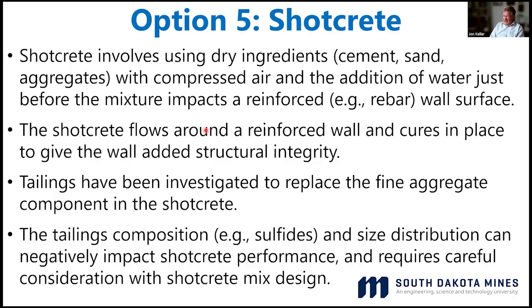Option 5 is shotcrete. Shotcrete involves using dry ingredients, cement, sand, aggregates with compressed air and addition of water just before the mixture impacts a reinforced wall surface, typically with rebar. And so the shotcrete flows around the reinforced wall and cures in place to give the wall structural integrity. Tailings have been investigated to replace the fine aggregate component in the shotcrete. But once again, you have to worry about sulfides and particle size distribution. I found just a few references where shotcrete was being used, compared to, say, paste backfill, which seems much more common.